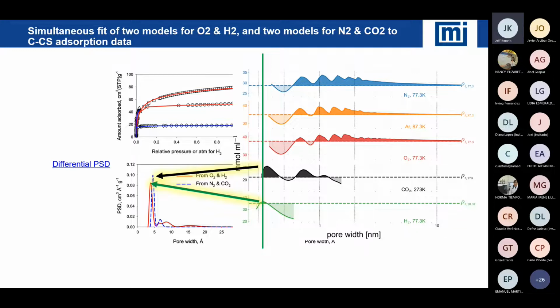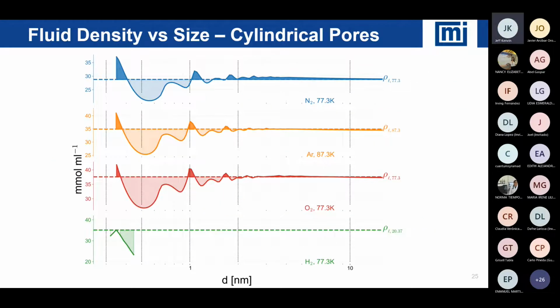It's parallel to all the other trends we see where having good simulation and good modeling improves our understanding of the experimental data. We can do the same for cylindrical pores. What is really critical about cylindrical pores and worth noting on this particular slide is the densities around 1 nanometer, that there are interesting areas around 1 nanometer where you can get very high densities. When you look to the left side, you see higher densities in that range of about 0.3 to 0.4 nanometers. Those are challenging areas. It's not so easy to attain adsorption at those sizes, and you'll see why very soon.